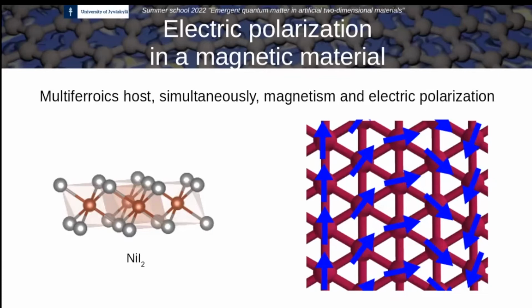And first, it's interesting to note that this lattice is frustrated by itself. And then one of the interesting things is that this material develops a spin spiral state. So this is not a ferromagnet. It's of course also not an anti-ferromagnet because it's a frustrated lattice, but it's also not a state with 120 degrees rotation. So it's something in the middle.